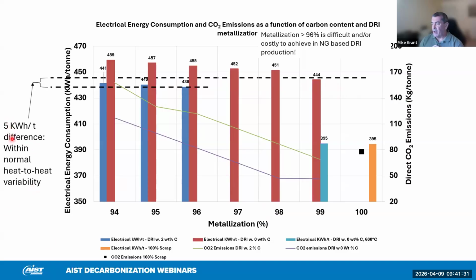theoretically there's about a 5 kilowatt hour per ton difference. And this falls well within the normal heat-to-heat variability. So essentially, this small difference you might not even notice when you're comparing the two.